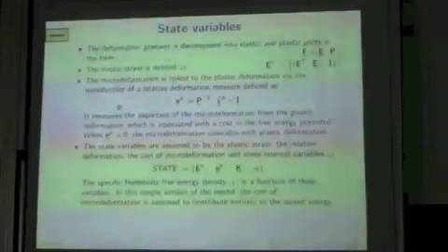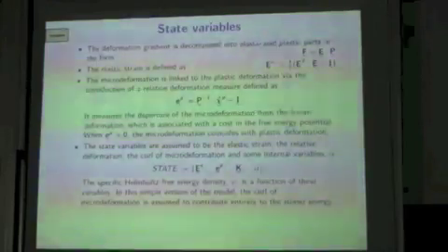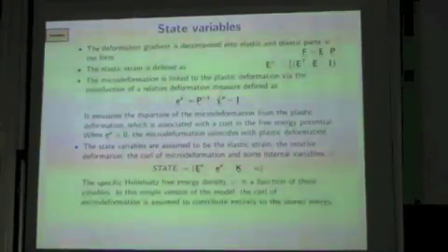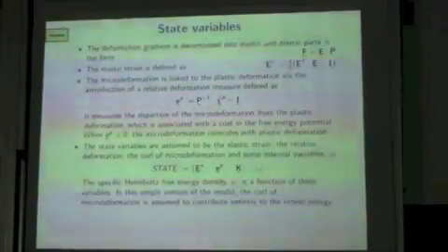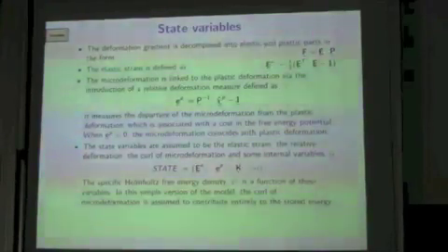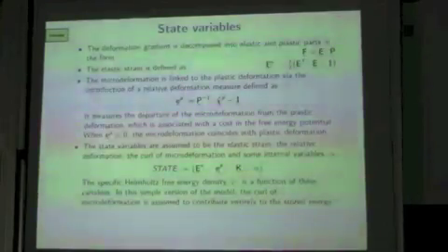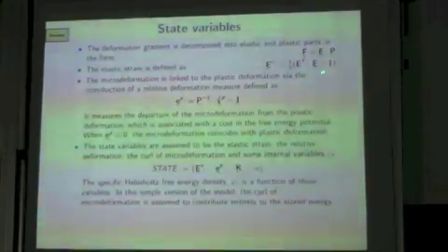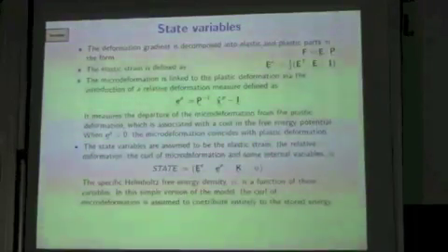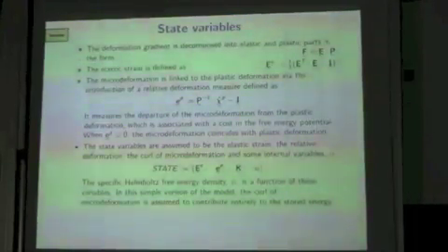Okay. We have to formulate some constitutive equations. We start from finite strain crystal plasticity, in which you split the deformation gradient into elastic and plastic part. Energy can be stored by means of the elastic strain. This is the Green-Lagrange strain, but with respect to the intermediate configuration in crystal plasticity.